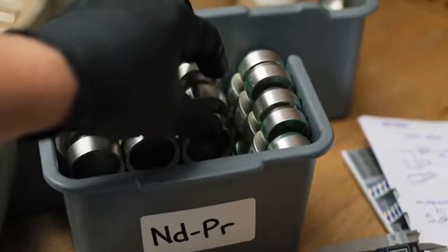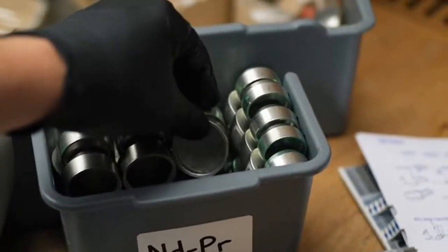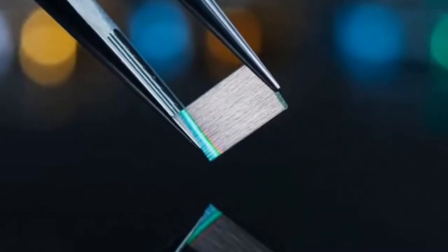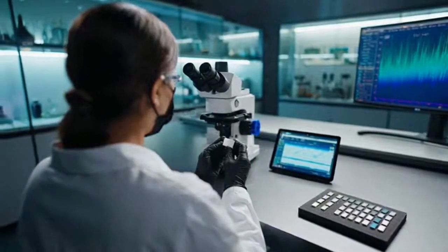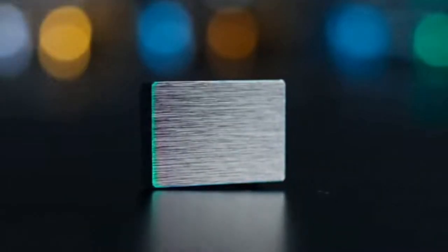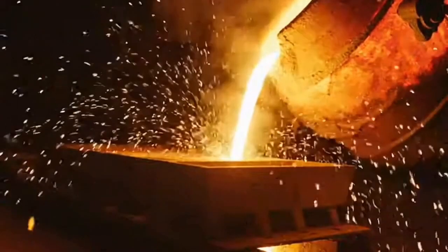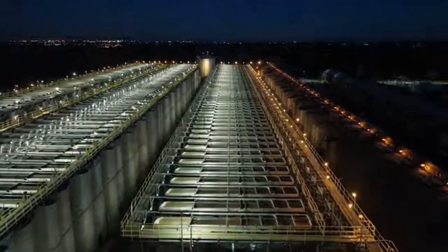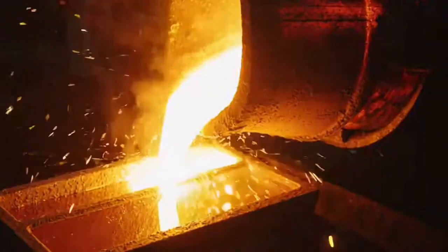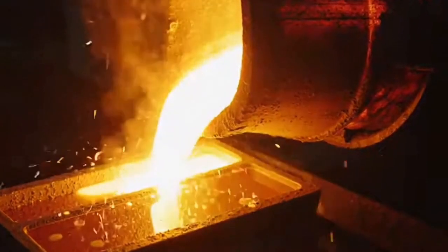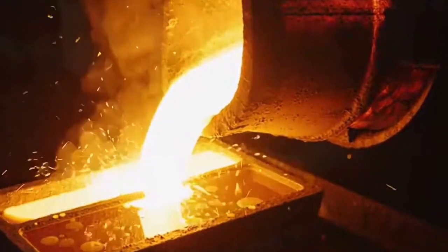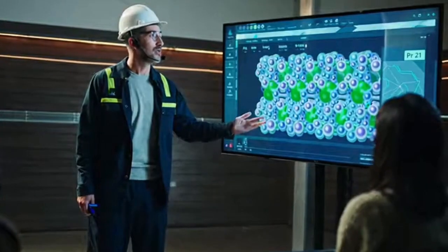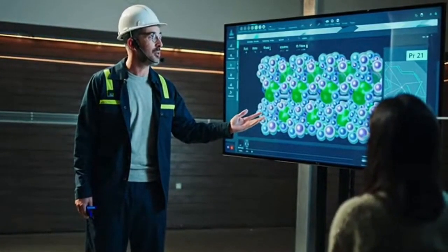The real trick comes at the grain boundaries. The way to make magnets survive heat without dumping expensive heavy rare earths is to treat grain boundaries like highways and diffuse small amounts of heavy rare earths, dysprosium or terbium, into them after sintering. That grain boundary diffusion pumps coercivity without poisoning the whole bulk with heavy rare earths that would lower magnetization. The matrix stays mostly neodymium and praseodymium, the boundaries get the armor.